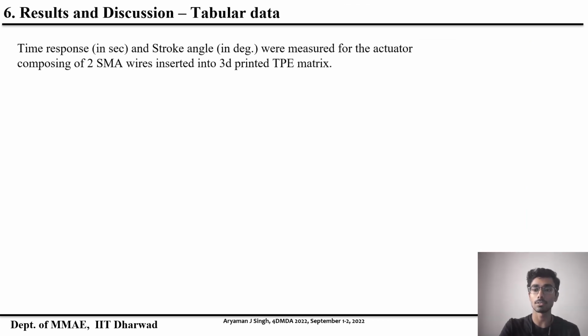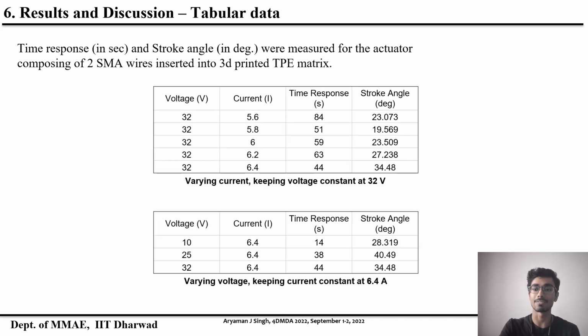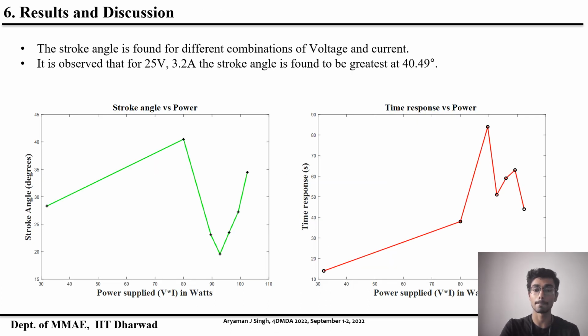This is the data on stroke angle and time response that we measured using the previously shown experimental setup. At first, the current was varied while voltage was kept constant at 32 volts in the voltage power supply unit. Secondly, we varied the voltage while keeping the current constant at 6.4 amperes. These are the graphs for stroke angle and time response plotted against the total electrical power.